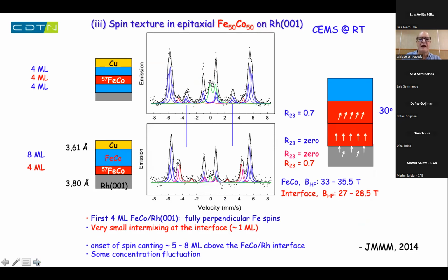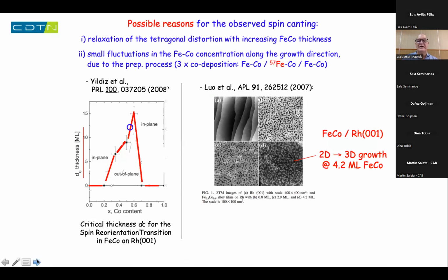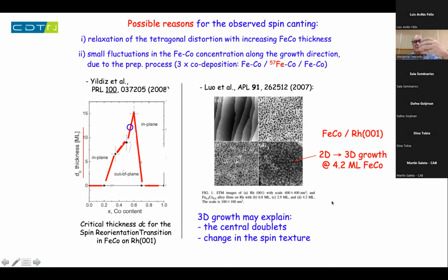And if you do Mössbauer, what we see is that if you put iron 57 at the very interface, you see that this blue spectrum does not show lines here. That means the spin at the very interface is really perpendicular. But if you go 5 monolayers away from the interface, we start to see some blue lines here, near lines 2 and 5. That means you have some spin canting. We start to lose the really perpendicular orientation of the spins, and we believe that this is because of the growth. That means above, let's say, 5 monolayers, we start to lose the layer by layer growth. We start to see some islands, and I believe that these islands are responsible for the spin canting that we observe.